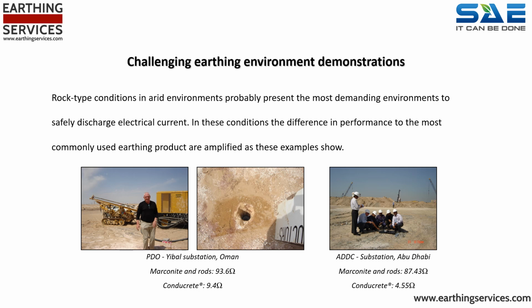Here we see a comparison in the desert areas of Oman and Abu Dhabi. At the first site, Conducrete achieved a resistance of 9.4 ohms compared to 93.6 using rods and marconite. And the second site, Conducrete achieved 4.55 ohms compared to 87.43 using rods and marconite.